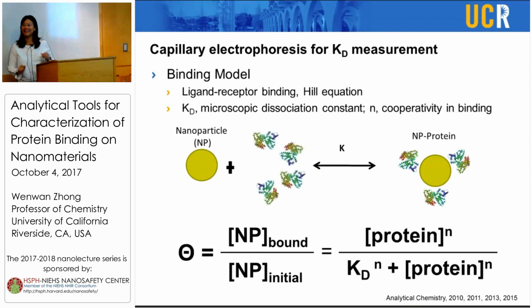Okay. Yeah, because we believe the binding affinity can give us a quantitative measurement of interaction strength. So when you have a variety of nanoparticles and test the affinity with certain proteins, you can compare the interactions, and get some information about how the physical chemical properties of the particle contribute to the interaction itself. But this measurement is not trivial, because a lot of nanomaterials have optical properties that would interfere with the conventional measurement.